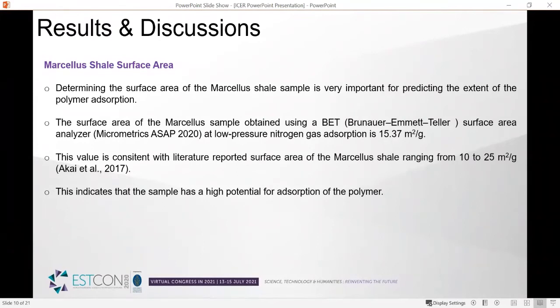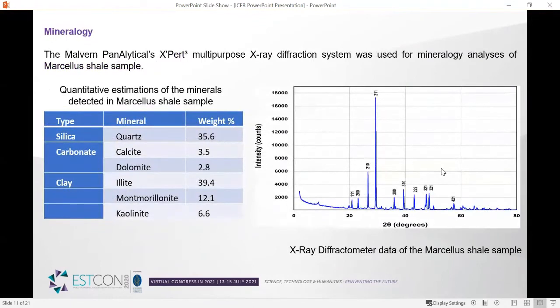So we have initially conducted the characterization test to find the surface area using BET for the crushed core, which is essential for adsorption. The sample had a high surface area of 15.37 meters squared per gram. And also we have looked at the XRD to estimate the contents of the Marcellus sample, and we can see that it mainly includes a high percentage of illite, which causes high adsorption, and that can explain the high surface area in the BET also.